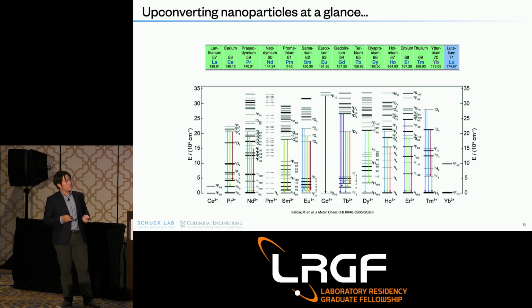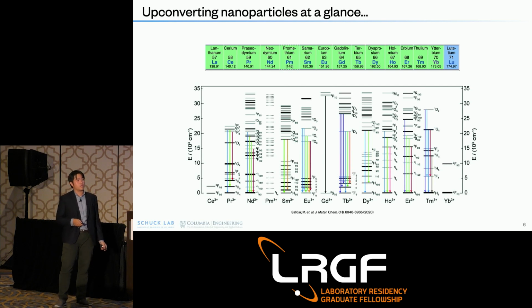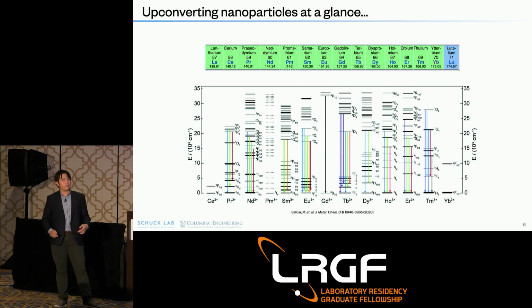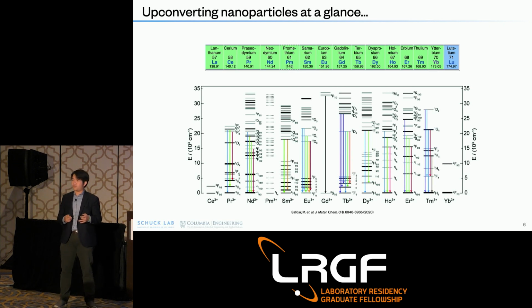Now, just to look into the spectra further for these lanthanide series, this is about, I think, 12 of them, but you can see that the energy levels really range from the infrared to the UV, and they're not just one or two, there's many of them. And I think this ties into my PhD a little bit better now. So if you start to pack many of these different lanthanide elements together, you can start to get very interesting physics known as upconversion physics.